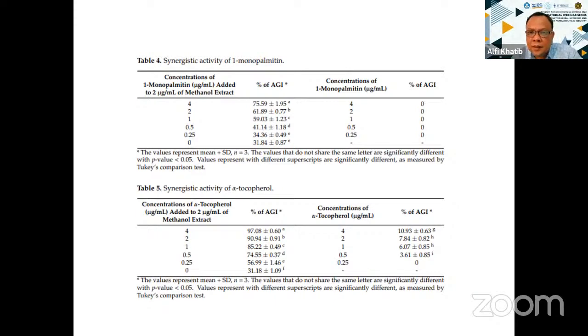Because actually there is a synergism effect of this monopalmitin or alpha tocopherol with other compounds. So what we did actually is spiking of this monopalmitin into the extract. Here you add 0, no adding, and then you add 0.25 micrograms per milliliter, 0.5, 1, 2, 4, and you find that there is increasing activity, meaning that there is a synergistic effect of monopalmitin with others. So metabolomics can explain that monopalmitin is the one which is active when it is in the extract, and when we try, yes, it's true. As well as alpha tocopherol: when you check individually, it's not active, but when it is in the extract, yes, the tocopherol gives activity, you see the increasing of the activity here.